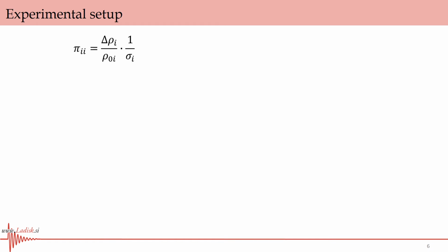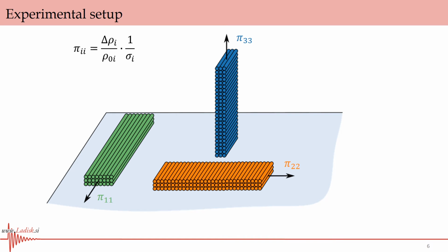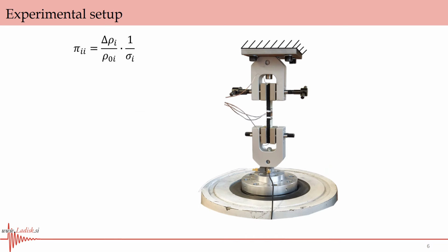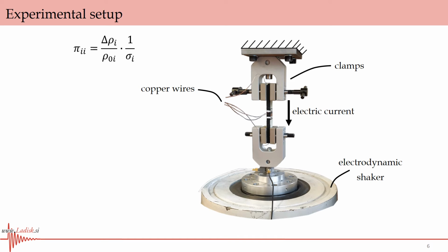Piezoresistive coefficient can be determined by applying stress to the FFF structure in one of the principal directions and observing resistivity and stress. To observe three distinguishable piezoresistive coefficients, three perpendicularly oriented specimen types were proposed. Specimen was then clamped to the electrodynamic shaker, and copper wires were used to transfer electric current to the specimen and to connect the specimen to external circuit used to measure electric resistivity.